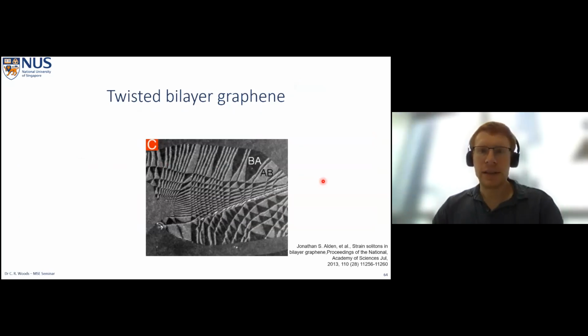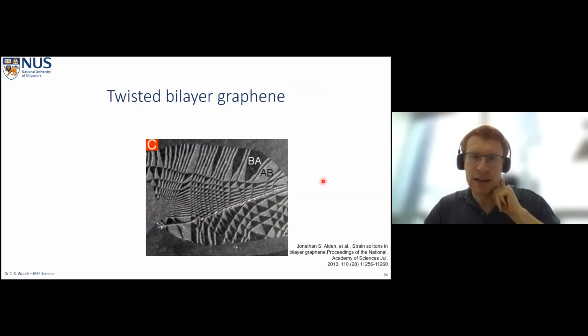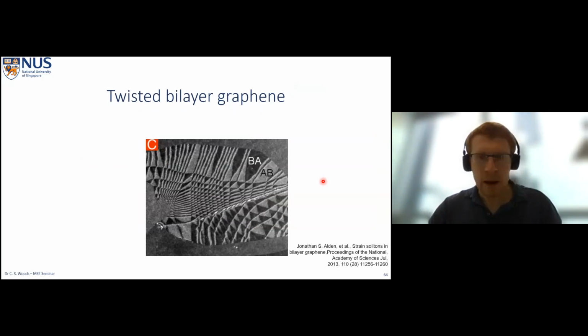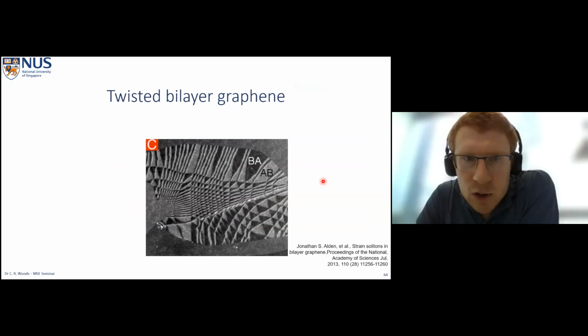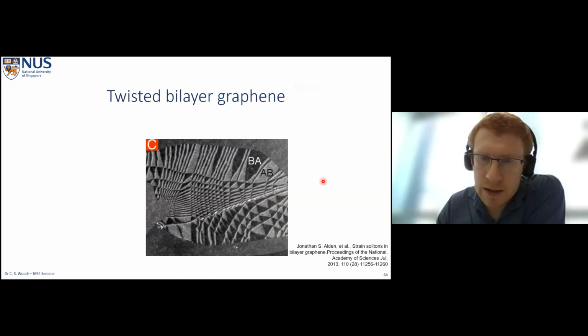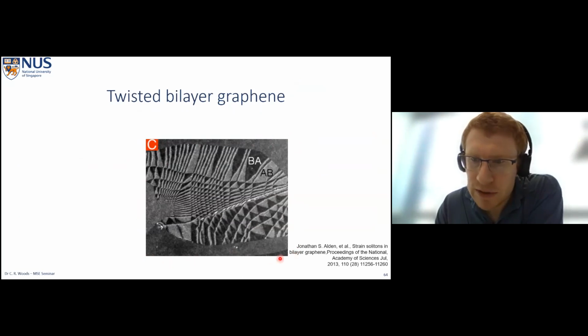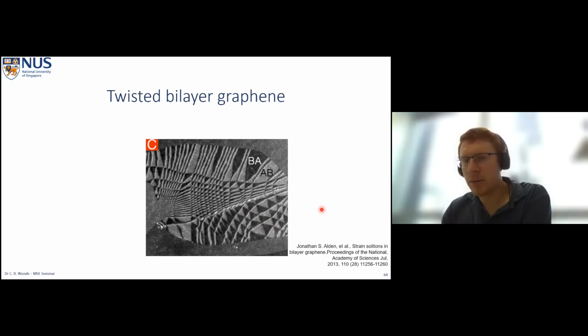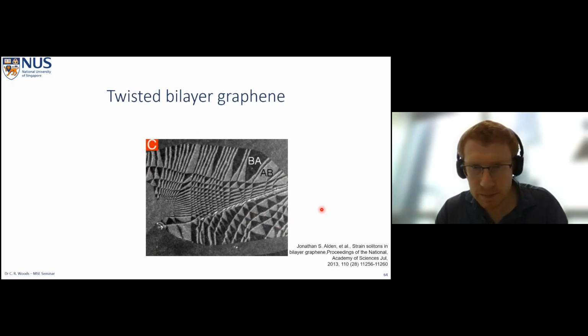So we can look at another system where we see similar triangles to try and understand our own system. And this is the twisted bilayer graphene system. This is an STM image of 2 graphene layers placed on top of each other. And this is useful for us because not only does it look very similar to our system, but actually for bilayer graphene, we can't have the anti-parallel configuration. Because graphene has 2 identical sublattices, we can only ever have the parallel configuration.